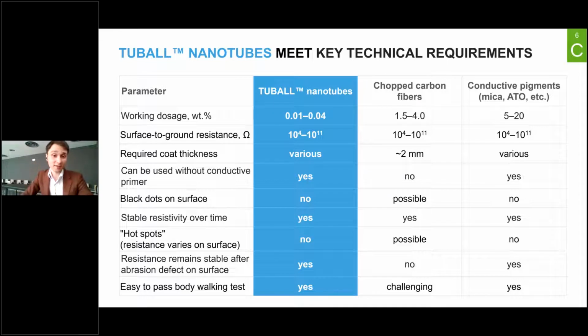I can tell you a short story which I have faced in my own experience. Our customer produced a top coating with our single wall carbon nanotubes inside, and they sold this formulation to their customer, which was a servicing company, the company which was applying this top coating. And then after the application, the end customer asked an external laboratory to test surface to ground resistance. And then they observed that there is no conductivity. Surface to ground resistivity was extremely bad. And then our customer, of course, approached OCSiAl and asked, "Okay, Andrew, how can we solve it? Because we have seen everything working in a laboratory and at other production facilities." So we arrived at this location and we tested surface to surface resistivity, and it was extremely good.